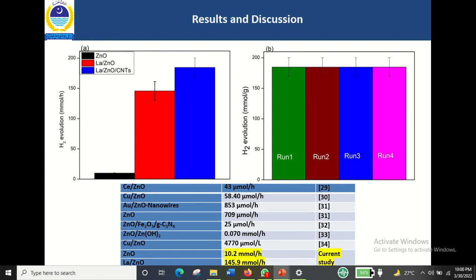These figures are much higher as compared to the previously reported results, which shows that the combination of rare earth metals with ZnO in the presence of carbon nanotubes can effectively be used as a photocatalyst for the production of hydrogen and the degradation of other organic pollutants.